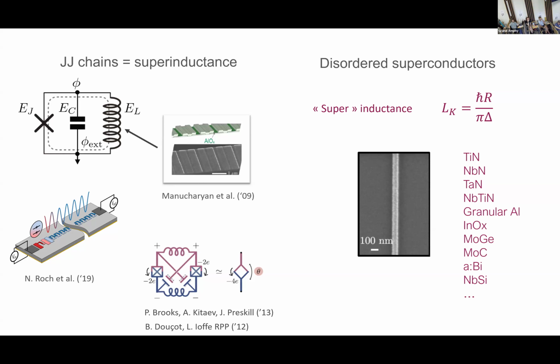But in principle, you can make the whole qubit from these materials. You can make the junction. You can make a parallel plate capacitor, which has also been done, and is in principle dangling-bond free. TLS should be very, very good in principle. And the large inductance you can also make from single-layer niobium diselenide, which was recently measured to be about 1 nanohenry per square. So yeah, you can make a whole qubit.